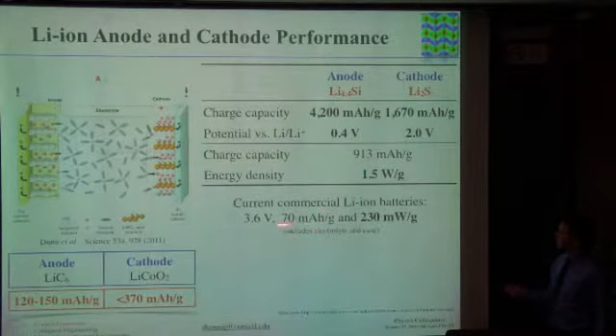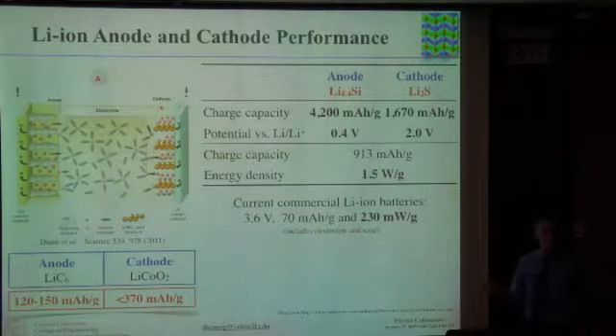If you compare that, here's data from Panasonic. The current battery you have in your cell phone has a voltage of 3.6 volt. It's 70 milliamp hour per gram and 230 milliwatt per gram. I got to be honest, we don't include in our estimates the electrolyte, which isn't actually that heavy, and the case. So our numbers should be reduced by something like 30% or so to account for that.